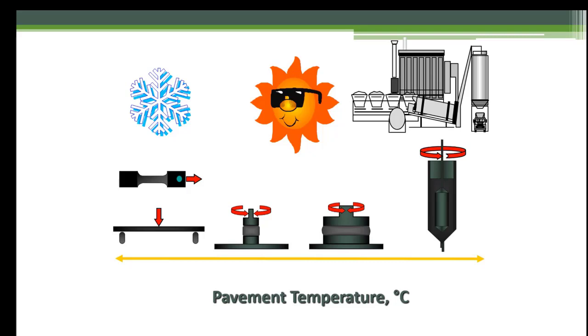And, you know, it might be a transverse crack on a roadway, and might be 50 foot to 200 foot spacings. And then next step to the right was a test that looks at, okay, what about normal operating pavement conditions? We want to assure that. And then third and fourth to the right, the third one is what happens at extremely high pavement temperature in the summer. Or far to the right, the fourth one, is what about when we're pumping and storing that and we're running it through a drum with the burner blowing hot superheated dry aggregate through it. So it accommodated all of those conditions.